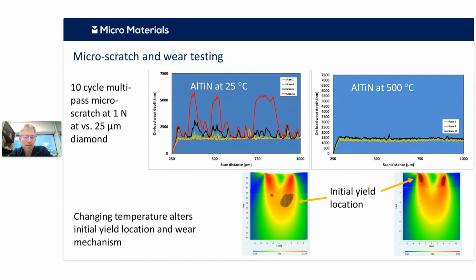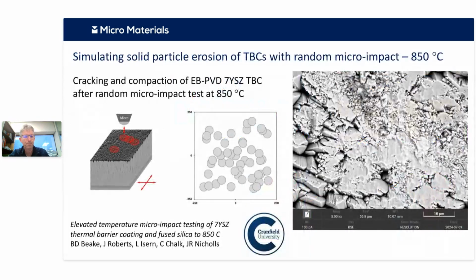If we do that same test at high temperature, then it was more resistant. And subsequent to that, we could understand what was causing that in view of how the failure location was changing as a function of temperature due to the mechanical properties of the system changing. So that's something where we're using indentation and scratch data together to improve our understanding. So again, it's this multifunctionality in the system.